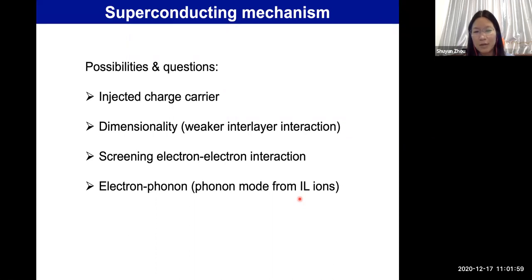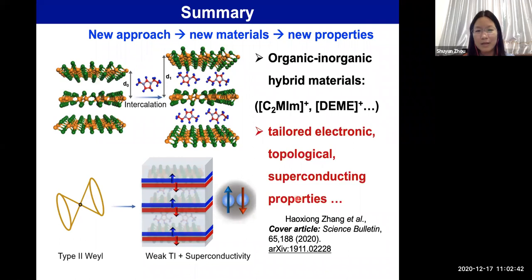Other possibilities include, say, a change in the screening of electron-electron interaction, or maybe electron-phonon interaction, or even electron-phonon interaction with phonons from the ionic liquids. So the superconducting mechanism is at this moment not clear yet, and I hope that more experts in this field will become interested in this material and look into this superconducting mechanism together with us. So by intercalating these large organic cations, we can tune the topological property and superconducting property of the material.